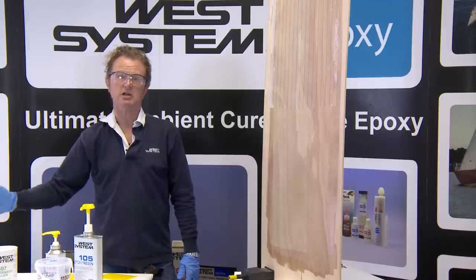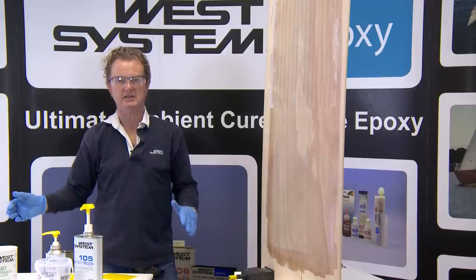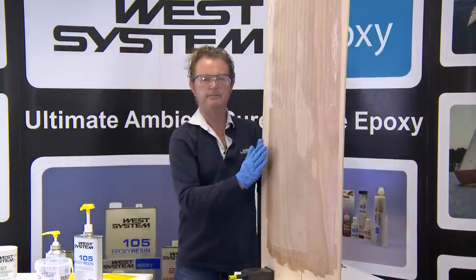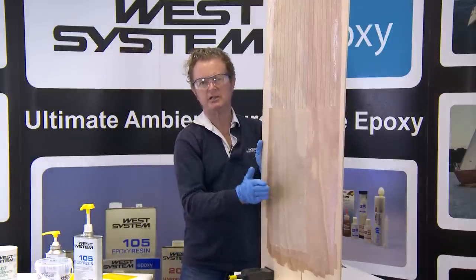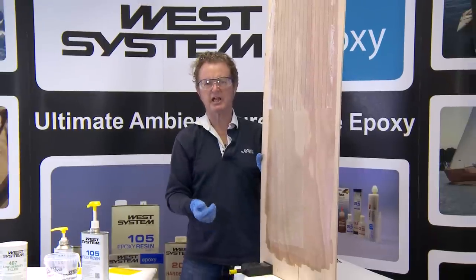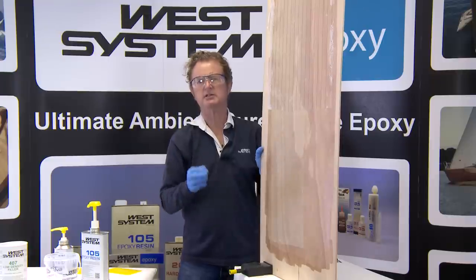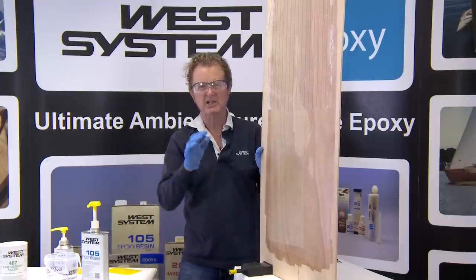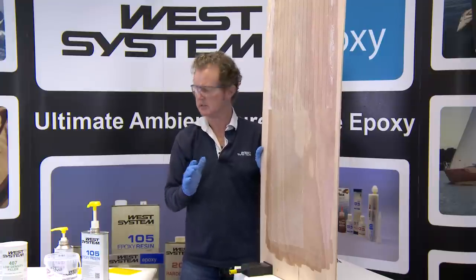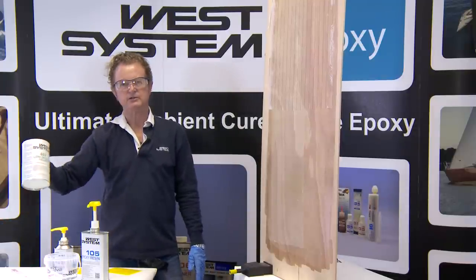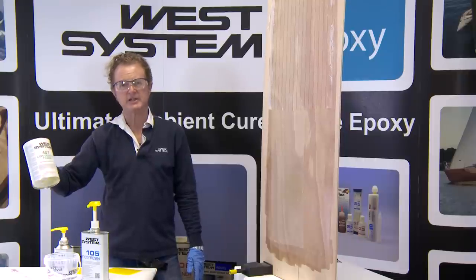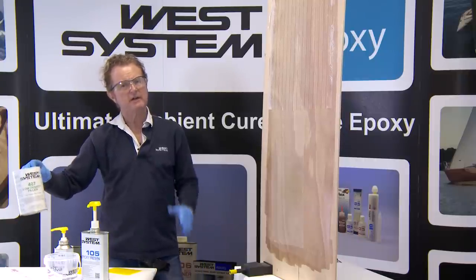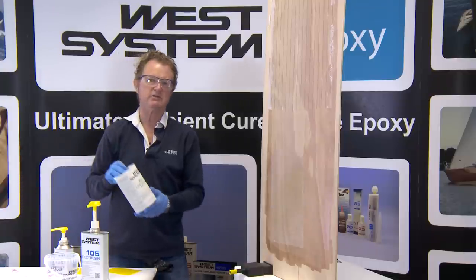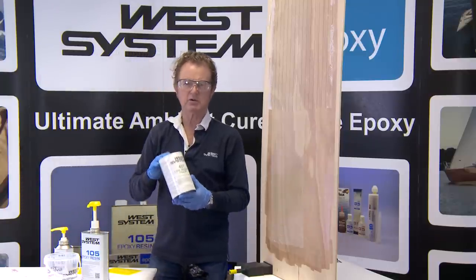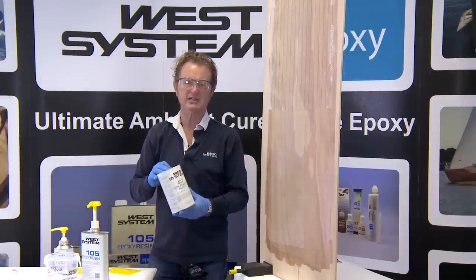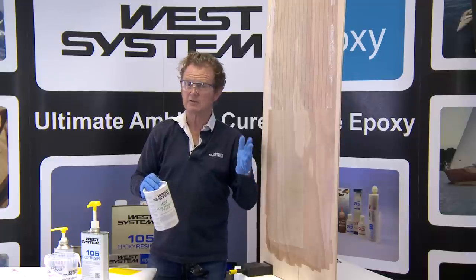The 410 microlite filler is the easiest to sand. In fact, it's almost the same density as cedar to sand. Very, very easy to sand, but not recommended under dark painted colours because it lacks a little bit of heat stability. The 407 low density filler is a fantastic stable filler that is also fairly easy to sand. The density of this is very similar to mahogany. So it does represent an easier to sand surface than just an epoxy coating, which is very, very tough to sand.